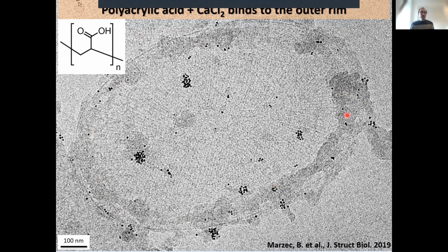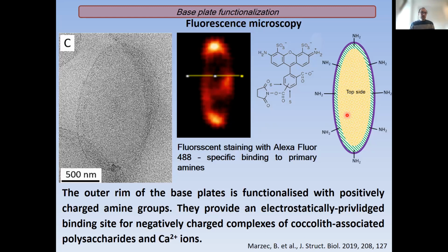Because this is a biological substrate, any positive charges would very likely be deriving from primary amines, could be from aminated polysaccharides or amino acids like lysine. So what we did to test that was to use a fluorescent dye that is functionalized with the N-hydroxysuccinimide residue, which makes it complex specifically with primary amines that are present on a substrate. And this is a fluorescent image resulting from this.